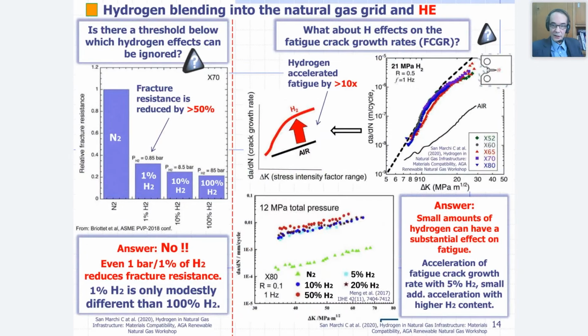So, hydrogen blending into the natural gas grid and hydrogen embrittlement. The first question on the left: is there a threshold below which hydrogen effect can be ignored? The immediate answer is no, because even 1 bar and 1% in the blending mixture of hydrogen reduce fracture resistance of steel. So 1% hydrogen blending is only modestly different from transportation of 100% pure hydrogen. As you can see on the diagram, we have a fracture resistance drop by 50%, even in the case of 1% blending. This is the data for X70, and an additional but small drop when we raise the blending ratio up to 10% or finally 100%.